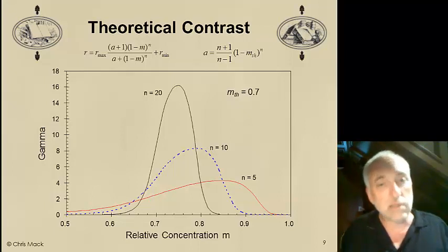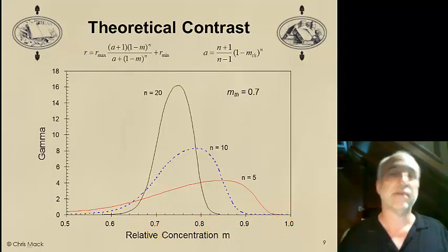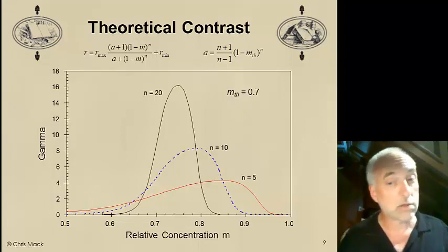But that's not the only thing going on here. There's also a dose dependence, a dependence on the relative inhibitor concentration. And it says when I have a high value of N, I need to use higher exposure doses to get high values of gamma or contrast.